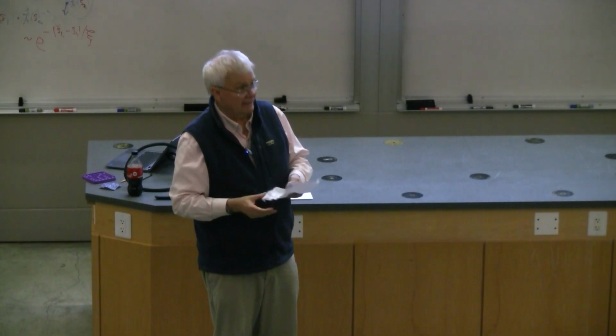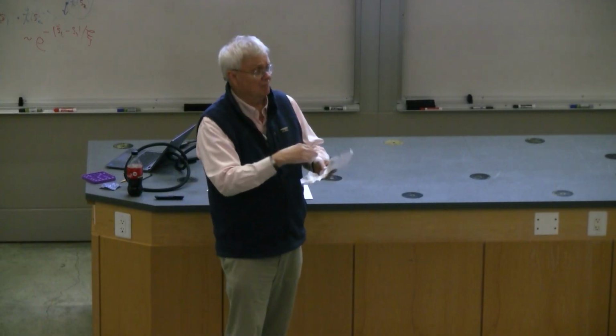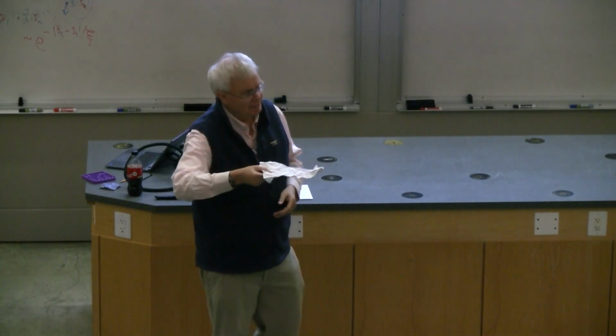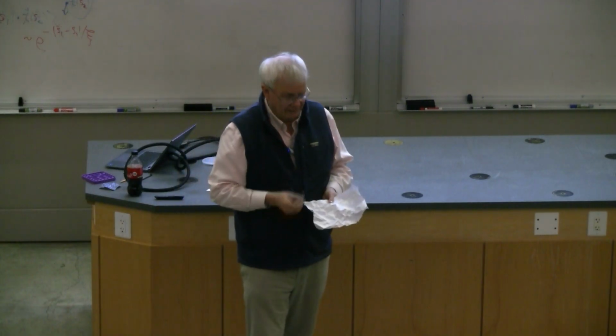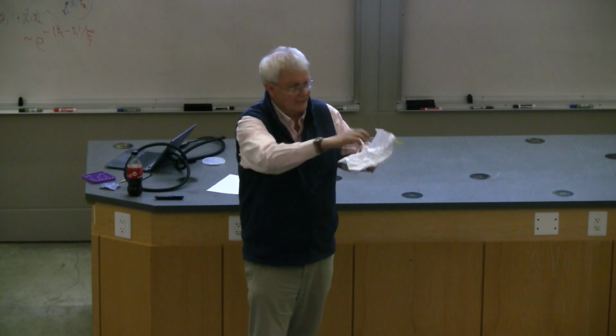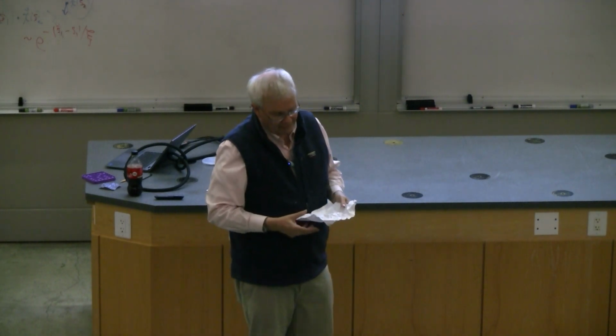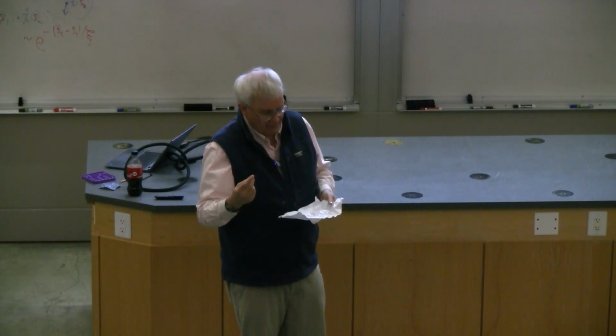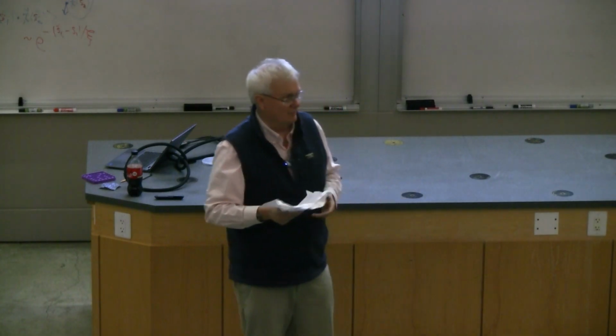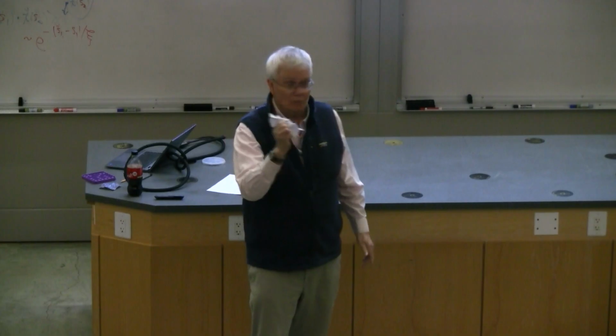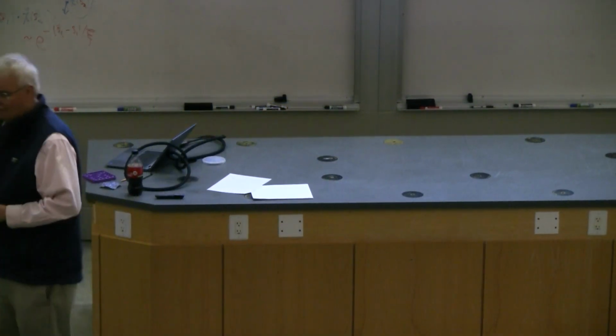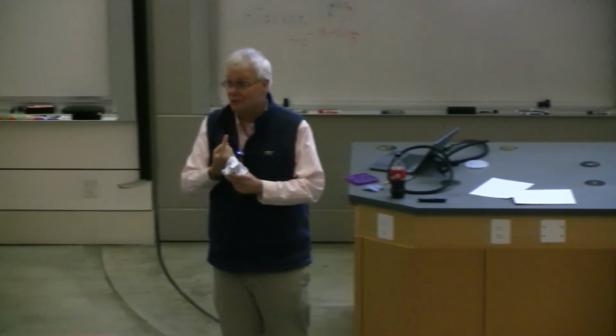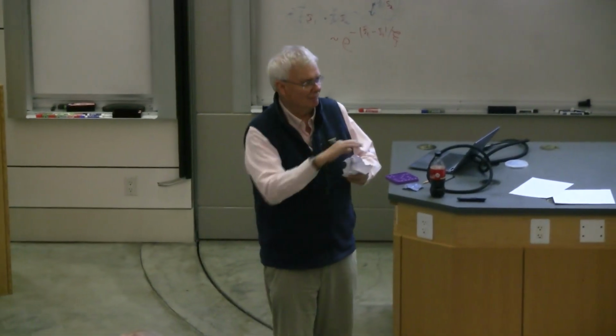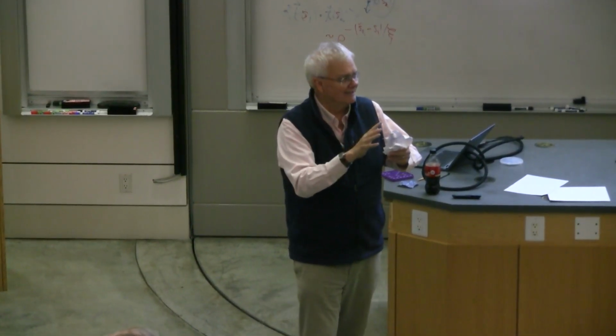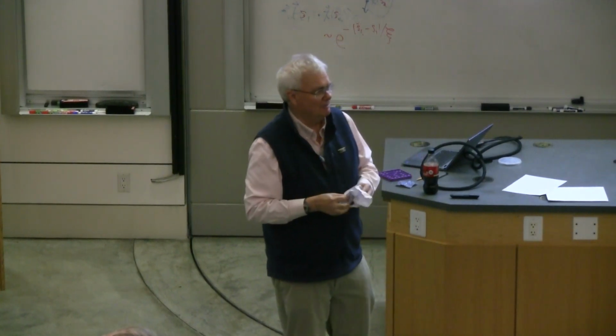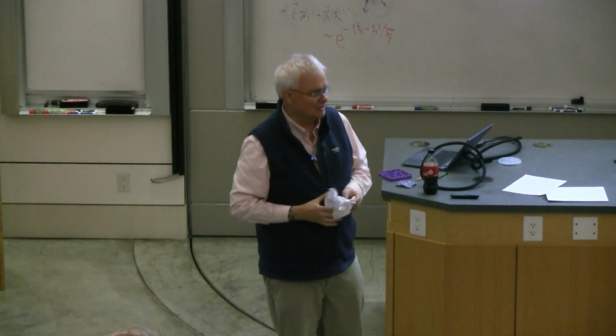You could still try to get it by cutting out a regular lattice of perforations. If you remove about 80% of this, as my colleagues Mark Bowick and David Yllanes have studied, if you just put a regular lattice of holes in this thing, it will no longer crumple at 20,000 degrees Kelvin, it will crumple at 1,500 degrees Kelvin, which might be more accessible in the lab. And then, boy, if you could crumple graphene, you'd have a baby version of general relativity with Dirac cones for the electrons. So it's quantum mechanics and fluctuating geometry. Doesn't get any better than that. So here at Stanford, I have hope that somebody will actually make this thing crumple, and we can start asking interesting questions about crumpled sheets.